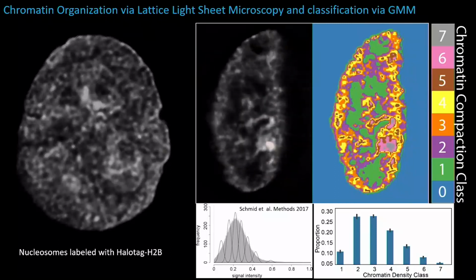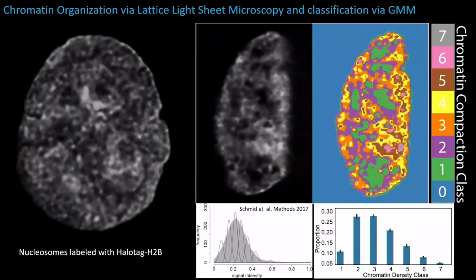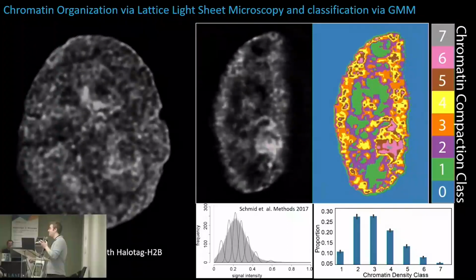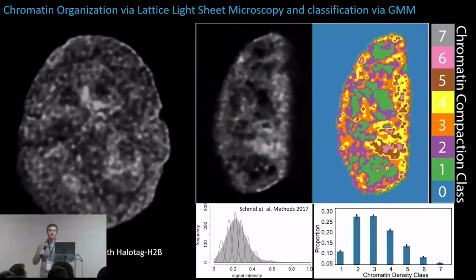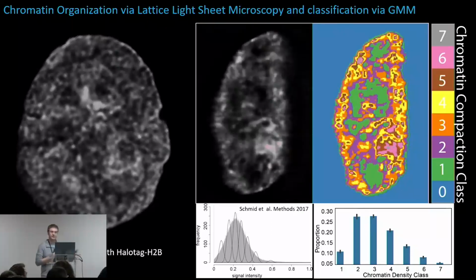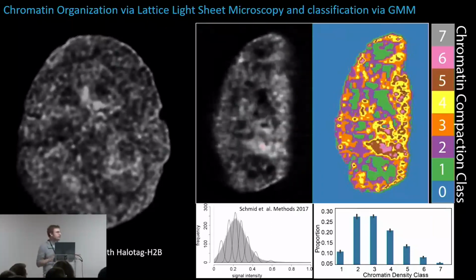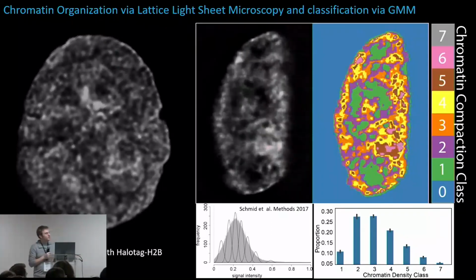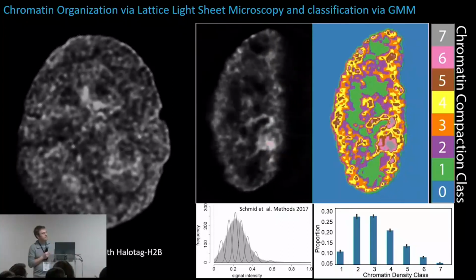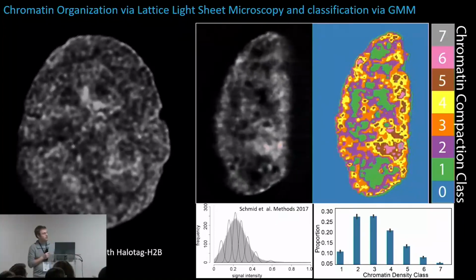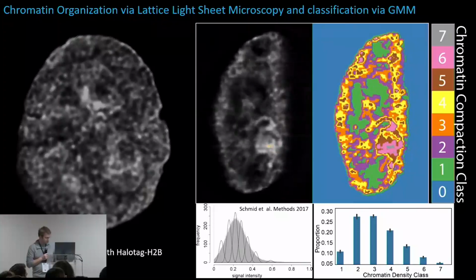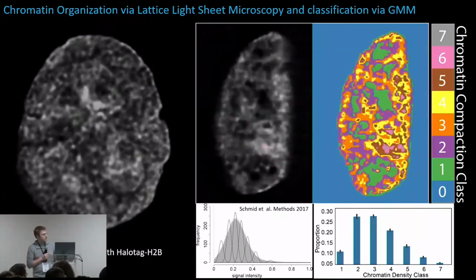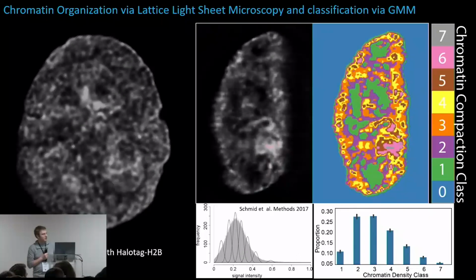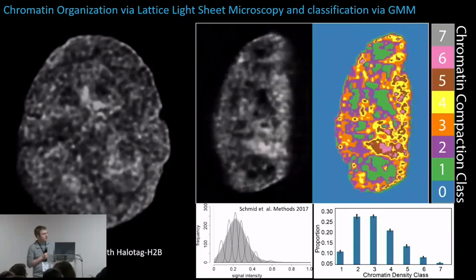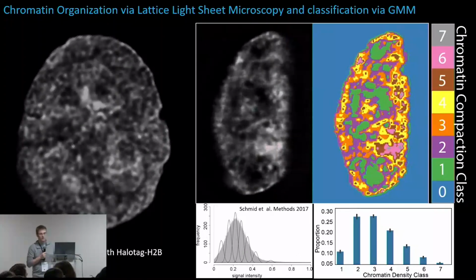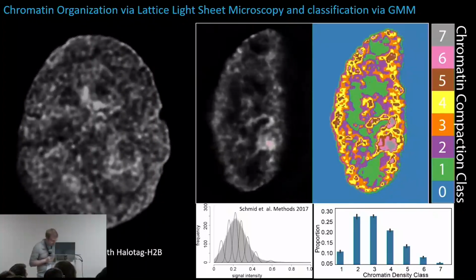And for sake of the next few slides, very dense heterochromatin regions, and I'm using heterochromatin admittedly very loosely because we're simply quantifying chromatin density, not, say, post-translational modifications one would normally associate with heterochromatin. But chromatin dense regions are going to be classes 7, 6, and 5, and then chromatin very sparse regions are going to be 1, 2, and 3. And so immediately we can see that the majority of the nucleus is actually occupied by low to intermediate density chromatin, and very, very low density and very, very high density are occupying proportionally less of the nucleus.